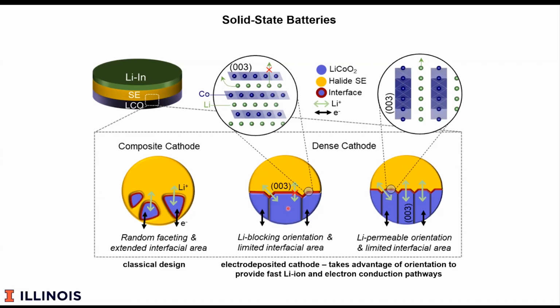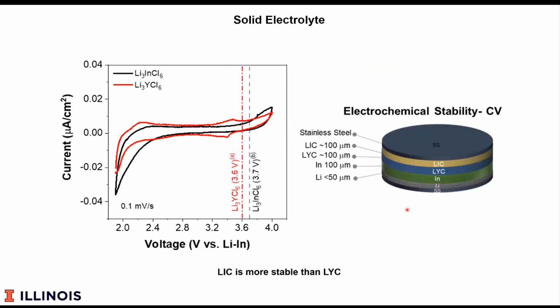What I would argue is by moving to a dense cathode that's engineered to provide fast ion and electron conduction pathways, this is really how you want to interface with the solid electrolyte. This is true for both the anode and the cathode of the system. Here we orient the material, remember, so we get the fast transport directions and the fast electron transport to be normal to the substrate, so it will interface effectively with the solid electrolyte. This limits the area and provides fast growth directions.